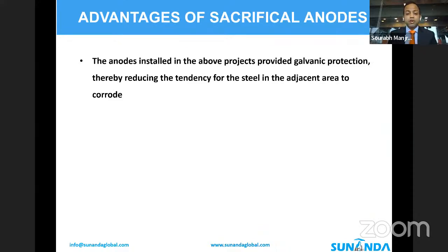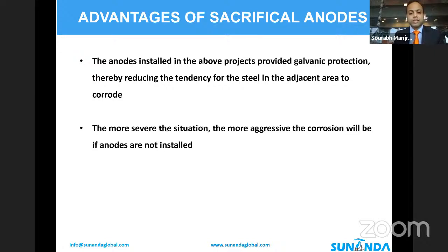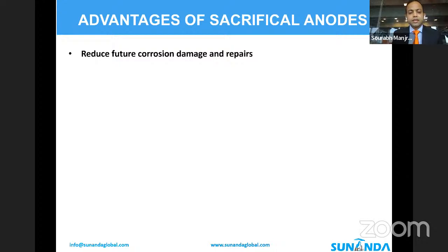The anodes installed in the above projects provided galvanic protection and thereby reduced the tendency for the steel in the adjacent area to corrode. The more severe the situation, the more aggressive the corrosion would have been in these structures if anodes were not installed. Anodes significantly reduced the future corrosion damage and repairs, and in turn added to the service life of these retrofits.